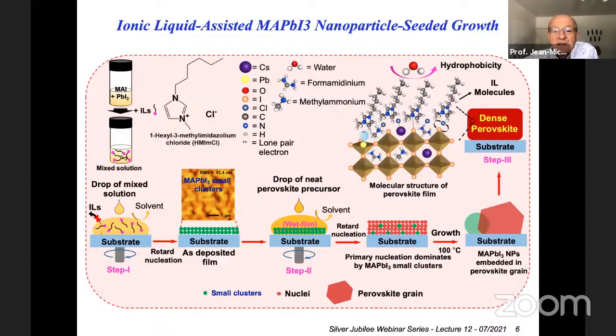And for instance, here is another work in which the trick was to grow larger crystals. So to grow larger crystals, there are different techniques. It looks a little bit complicated. That's a lot of experimental work to optimize these materials. And using a combination of ionic liquids, which allow to have a material which has different wetting properties for the different solvents that are involved in that material, and different growth techniques, we are able to grow larger crystals which will also be less wetting to water, so that could increase the stability. So you can understand that there is a lot of work which is done, but the main